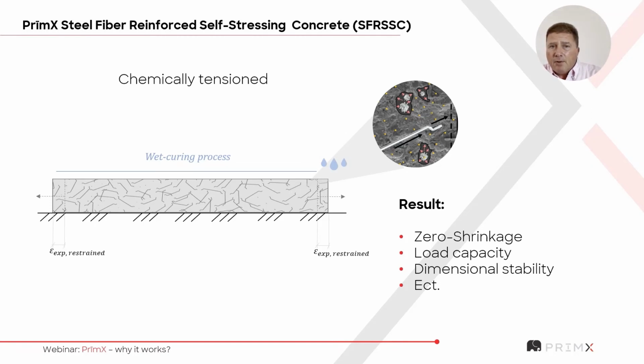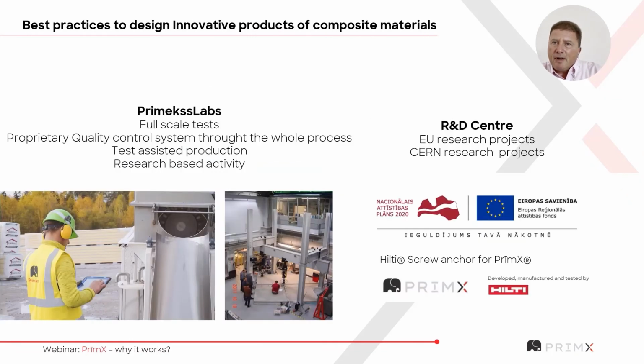as a company, PrīmX has to consider the fact that this is not something you can just let loose on the industry. We have to regulate it. We have to take care of the material itself to make sure that in the first instance, the concrete mix design that we come up with is bespoke to that area. So in other words, we're using the materials that you have available locally at the area, at the source, at the point of production. We're testing those in a laboratory. We're working out exactly the proportion of shrinkage compensating material that we need in there, and the type and proportion of steel fibre that we need in there to give us the mechanical properties that we need to satisfy the design.